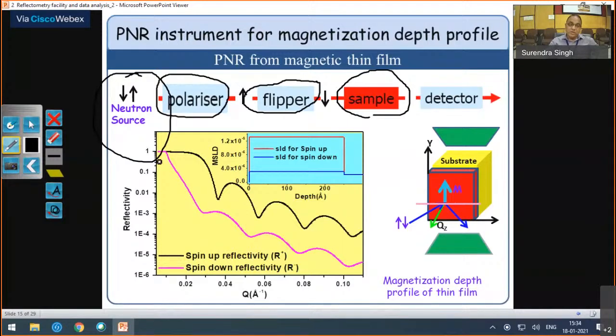A typical reflectivity pattern for spin up neutrons, shown in black, and spin down neutrons, is shown as a function of Q. The difference between spin up and spin down reflectivity gives you the total magnetization in the sample. This is just from a single film on a substrate.